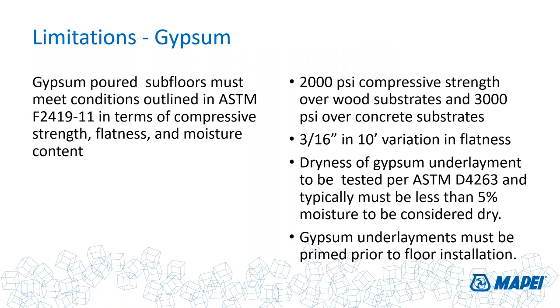Gypsum underlayments, there's an ASTM standard for that as well. Minimum requirements are a little bit less for that, 2000. Again, this is kind of driven by a residential market. There are a lot of gypsum-based underlayments out there that have compression strengths in excess of 5,000 PSI that work beautifully for commercial environments. But keep in mind that they take longer to dry. And there is an ASTM test standard for how to measure the moisture content of a gypsum slab.